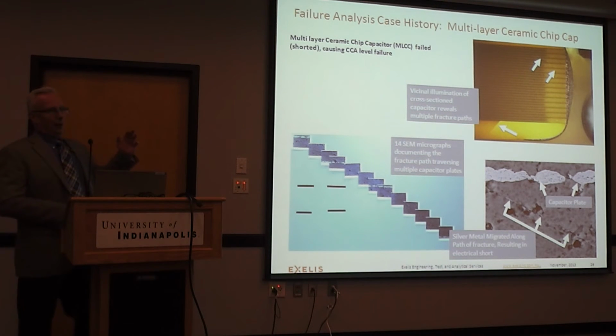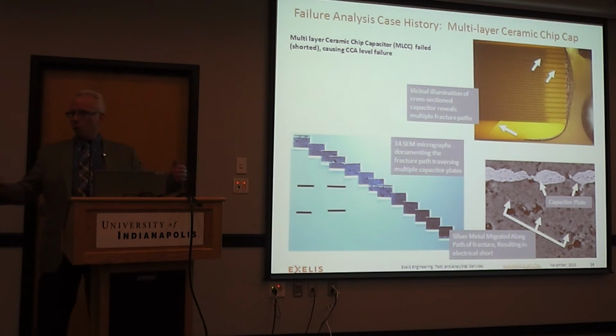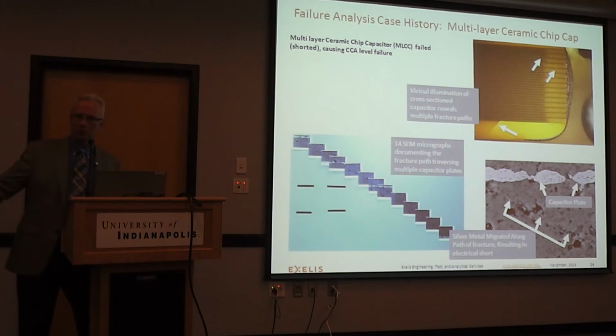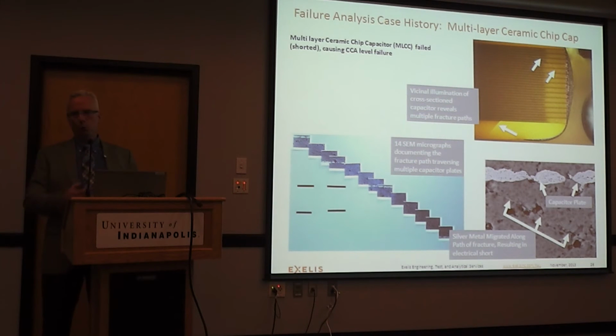So then, you keep asking why. Why was it shorted? Well, we had a fractured capacitor that provided ample opportunistic fracture path for electromigration. Why was it fractured? Ultimately, we did find an issue with stock capacitors from the supplier, and that turned into a very large screening process where we screened a lot of stock capacitors before they were ever put into products. So it was a high reliability program. The customer could assume no risk or little risk, so we mitigated risk by scrutinizing everything before it got put in product.